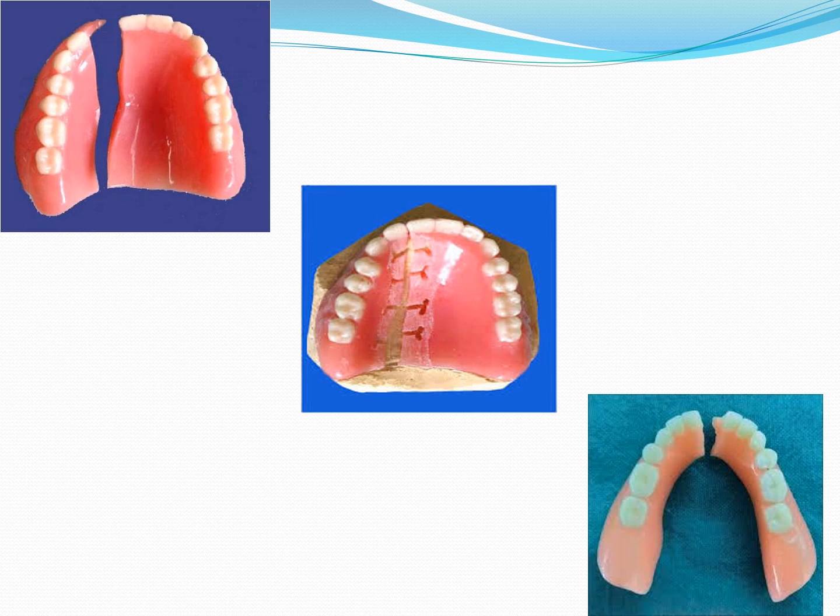There is wear of teeth. In a single complete denture, we saw that the lower anterior teeth have a hammer-like effect on the upper maxillary denture, and from the relief area there is usually a midline fracture, especially when natural teeth are opposing. They are giving extra force.